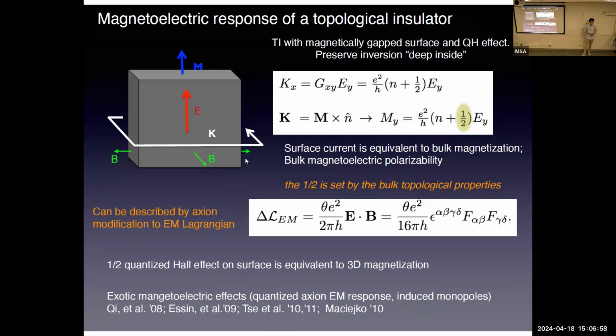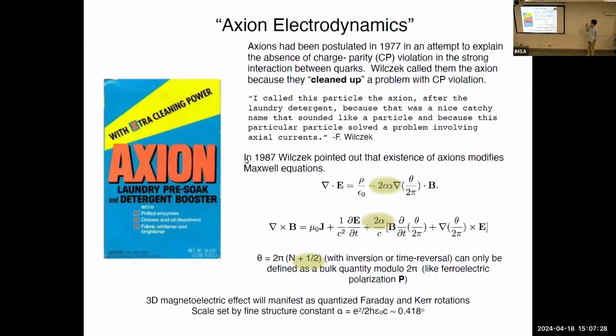is an axion angle, basically, and it's equal to, according to some symmetry considerations, it's constrained to be an integer times pi, and it's an odd integer times pi for the topological insulators, and an even number multiplied by pi for trivial insulators. And then, yeah, this is the detergent I was talking about on the first day.